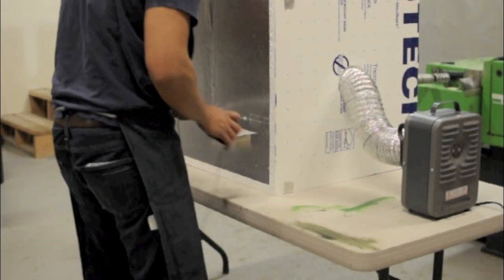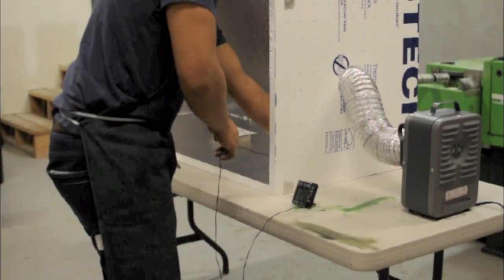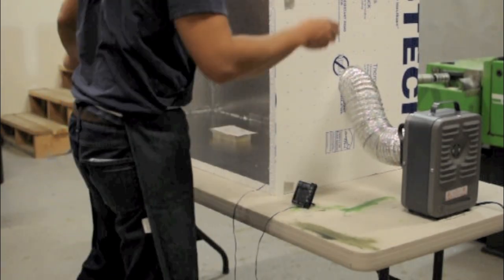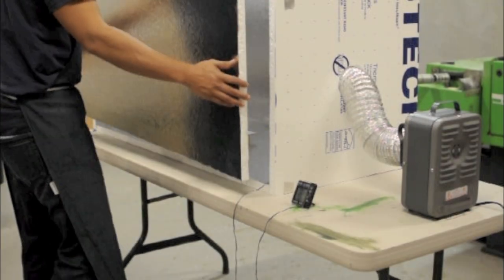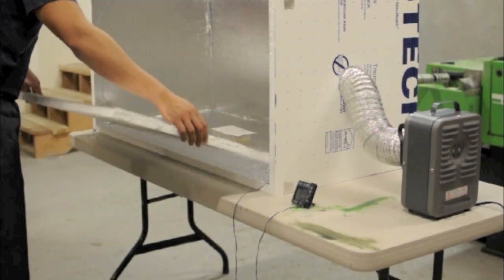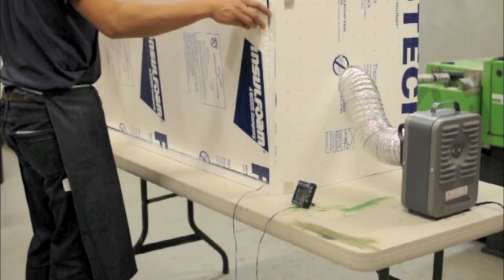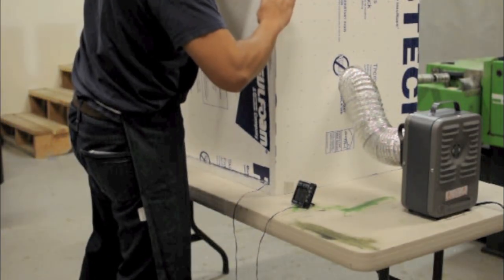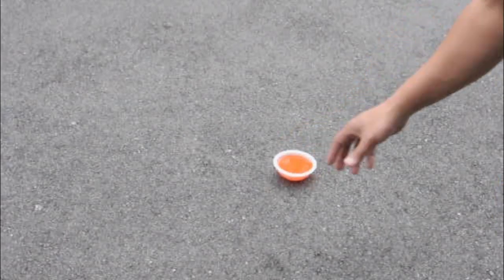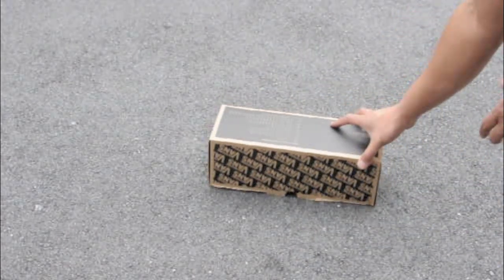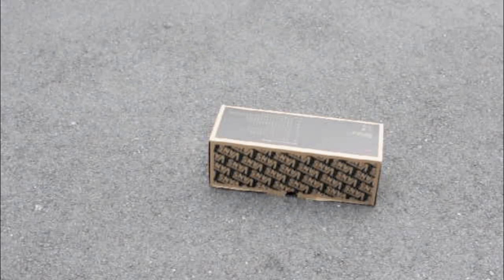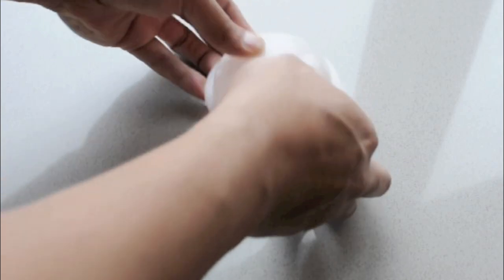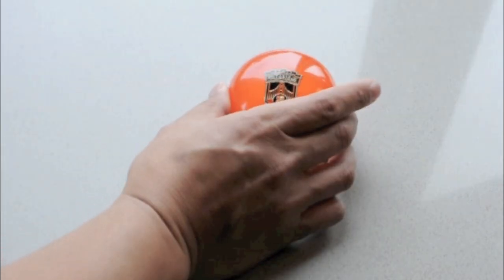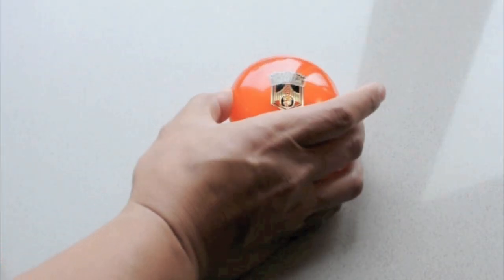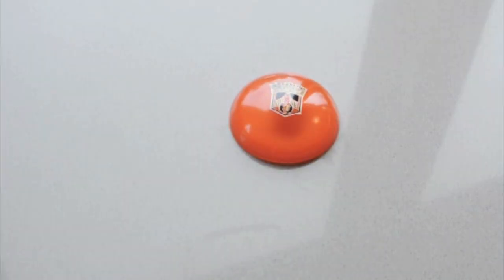Post-cures can be done by using a hot box such as the one shown here. They're easy to make using home foam insulation and a space heater. Because space heaters represent a fire hazard, never leave your hot box unattended. Another simpler method is to place your part in the sun over a hot surface such as asphalt and cover it with a black box. Once your part has achieved full cure, remove it from your mold and enjoy your work.